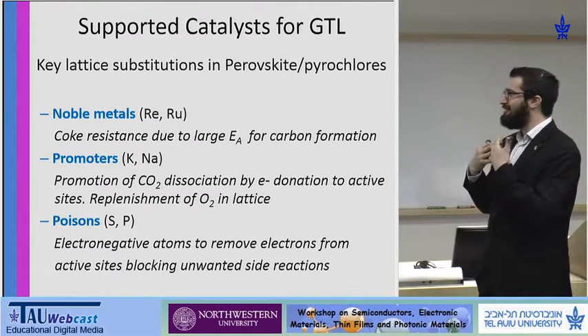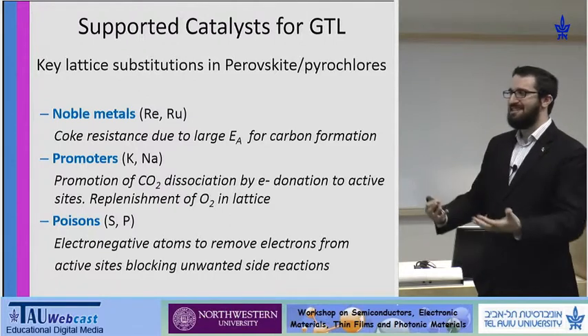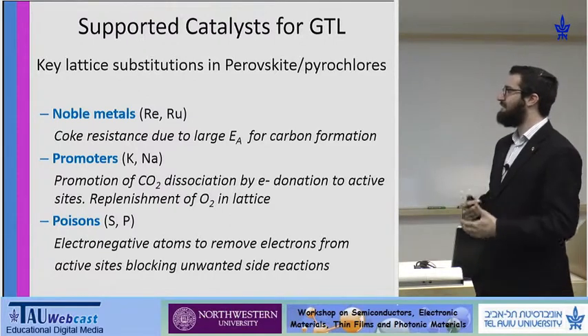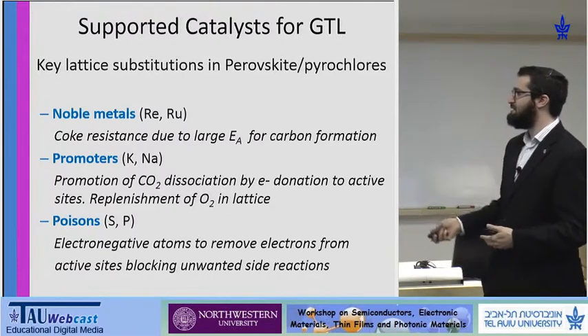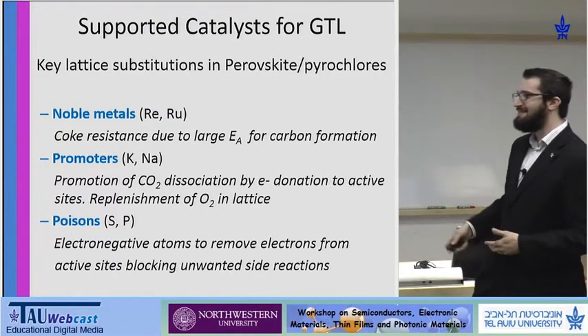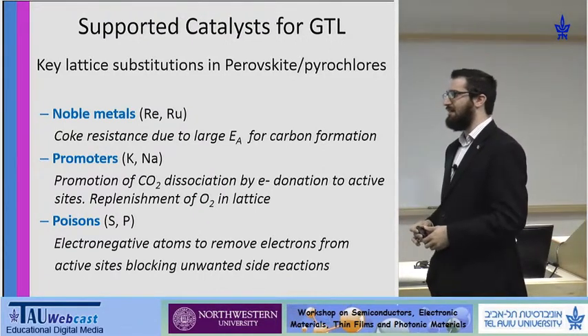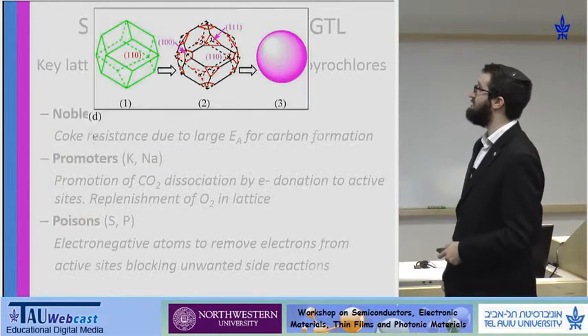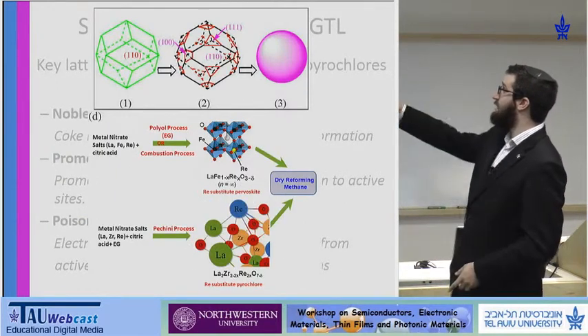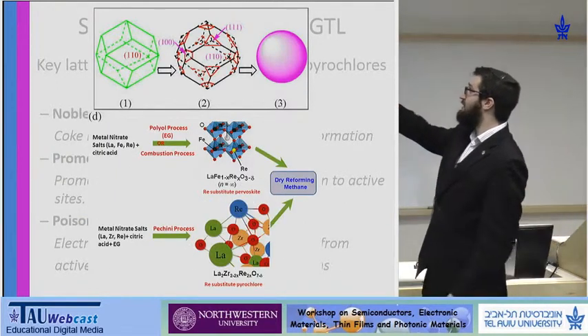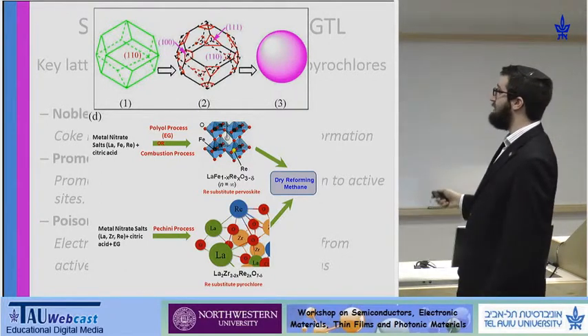But in order for the oxygen to be replenished into the lattice, we need to have a faster rate of carbon dioxide dissociation. And also, we can play around with poisons in order to selectively block side reactions. We can also play with shapes of perovskites, exposing different crystallographic orientations by shape control.